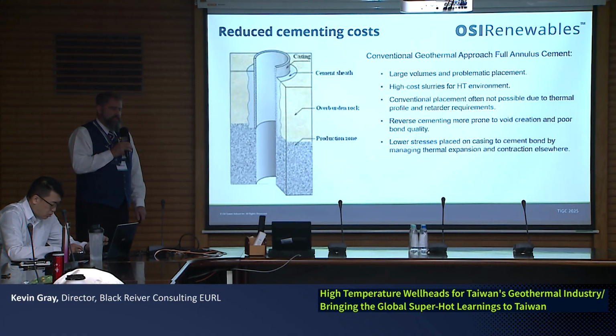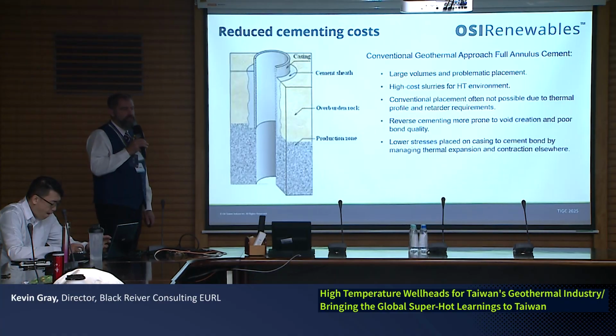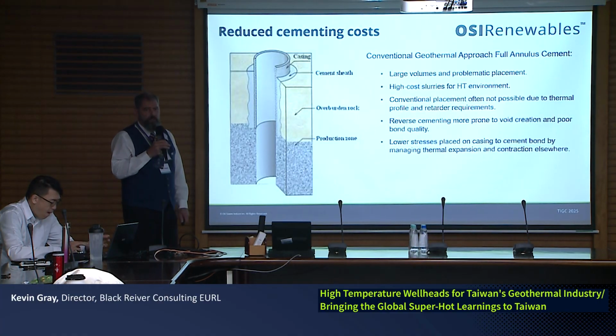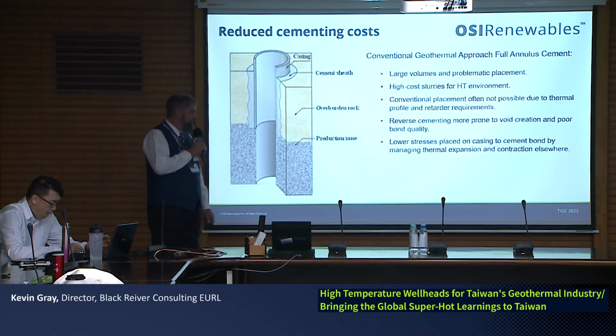So how do we get the cement in there if we can't go conventionally? What we might have to do is reverse the cement down the annulus and up the string. And the problem with that is that the actual cement placement and the isolation from the mud is not as good. So we typically end up with a lot more contamination, a lot more void space creation.